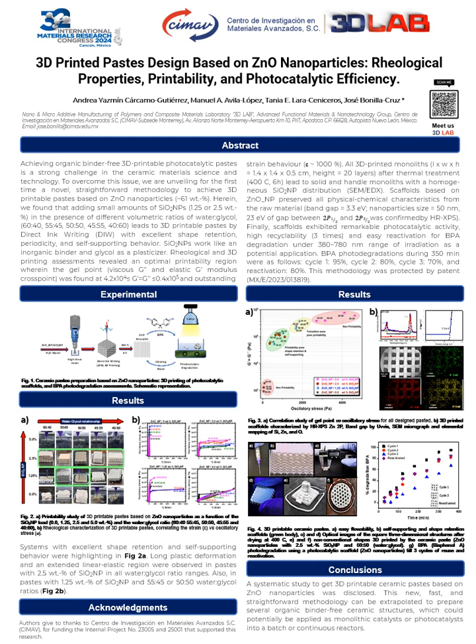and collapsed. In Figure 3, a printability zone was found, which corresponded to the gel point versus oscillatory stress of each print. That was where the prints with the desired properties are, the transition zone, which was the area where the ink could be printed up to certain layers; from there, it showed a lack of cohesion in the ink and was non-printable.